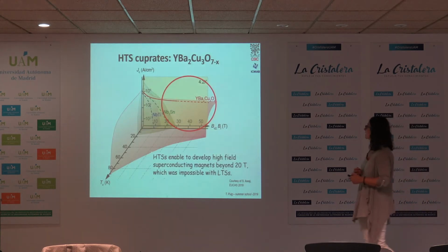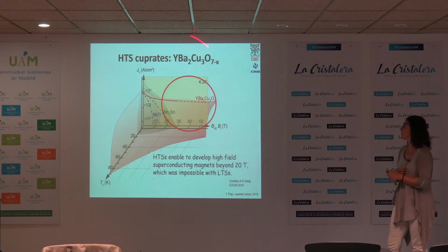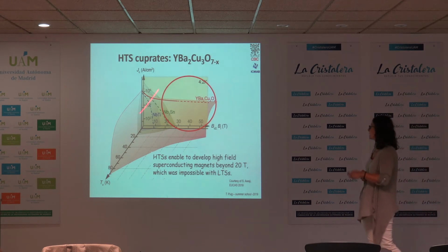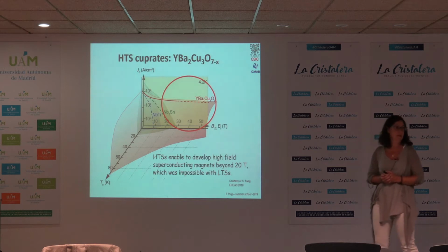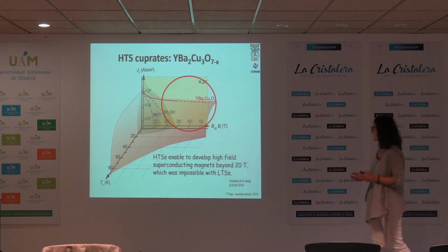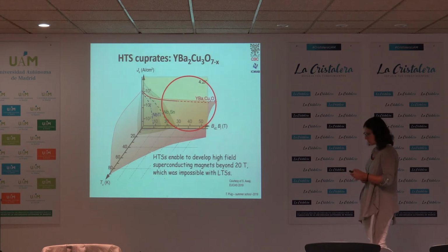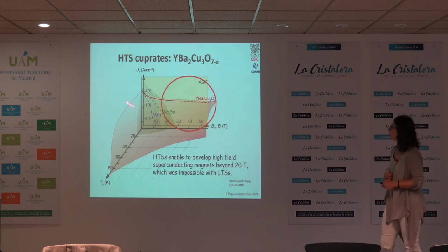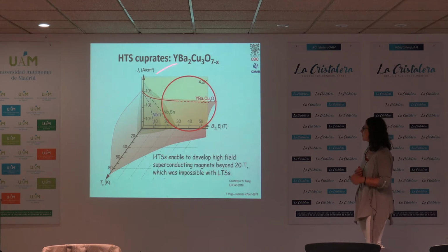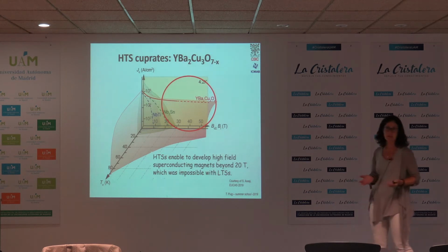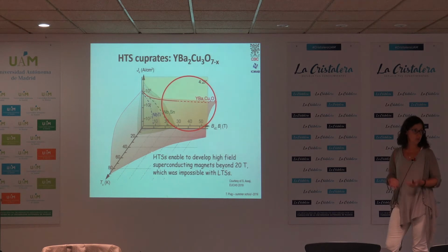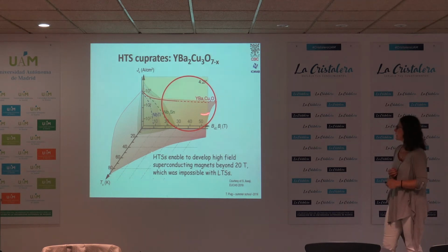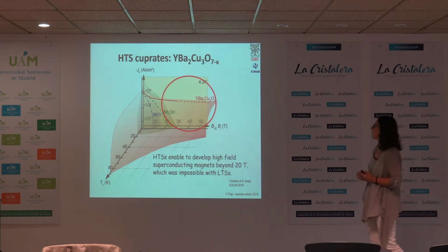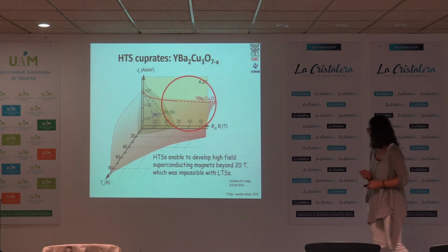And what I want to stay longer on is the cuprates, because YBCO is the one covering the larger surface of the JC, BC, and TC area. We want to see what the situation is now. YBCO, which at the beginning was meant to be a superconductor for high temperatures, nitrogen temperatures, is nowadays also thought of for low temperatures, because we can go beyond 20, 30 Teslas for applications at 4.2 kelvin.